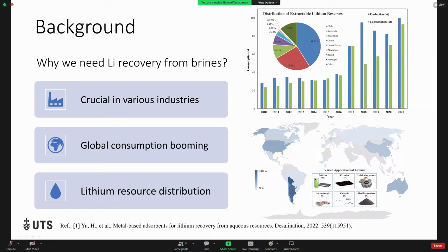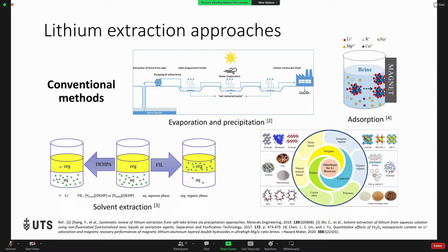On the other hand, lithium is abundant in aqueous resources. About 75% of lithium on land is stored in brines, and the reserve in the ocean is even over 60,000 times that on land. As a result, especially for Australia, a lithium-rich country, it is very significant to develop technologies for recovering lithium from aqueous resources. So far, the conventional methods to extract lithium include evaporation and precipitation method, solvent extraction method, and absorption method.